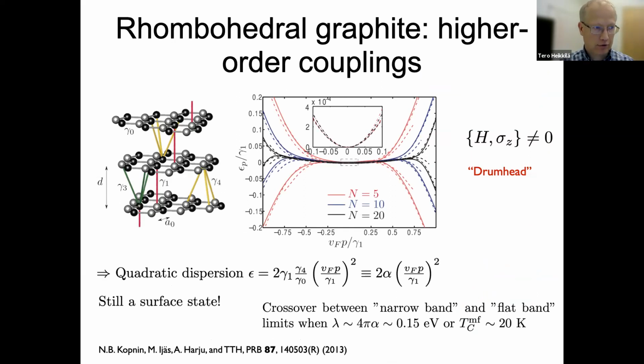One thing that they do is break a certain chiral symmetry of the Hamiltonian. And it's this chiral symmetry that protects the flat band, but even without it, you still have surface states, which are so-called Drumhead states. So there is some finite dispersion on the surfaces of these states. It's a quadratic dispersion characterized by a bandwidth alpha, which depends on the parameter gamma 4, and we estimated that this alpha has a certain magnitude.